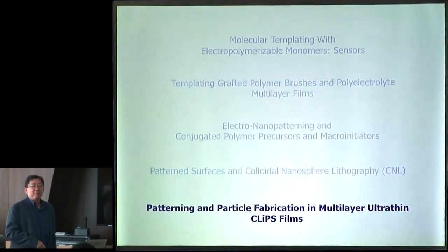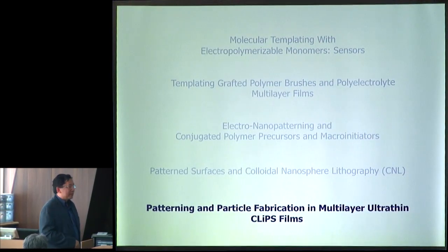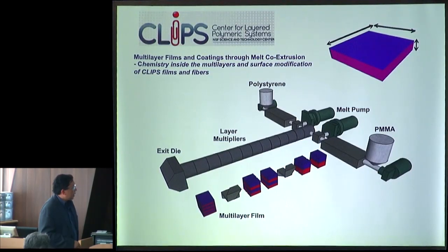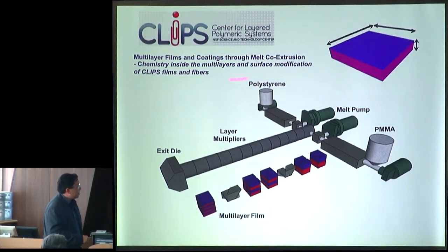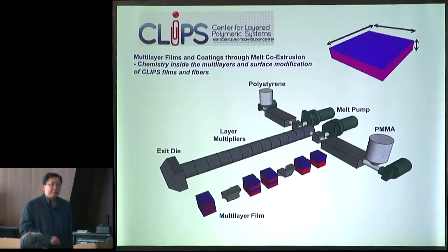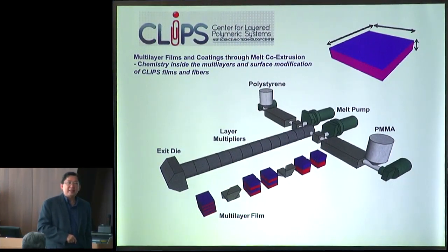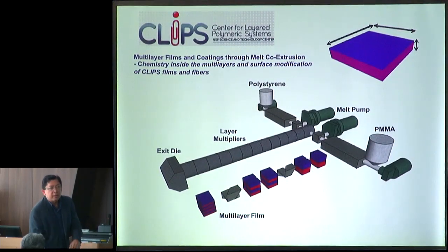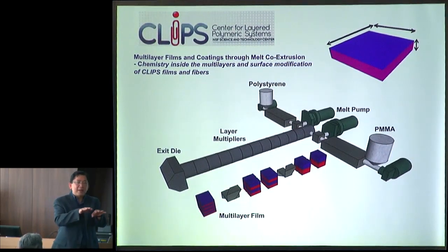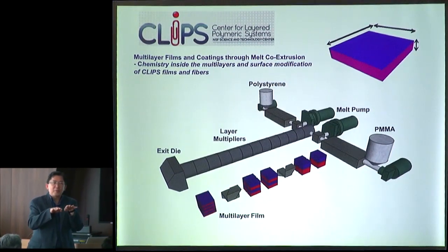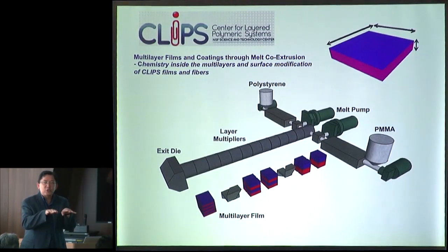So here is the polyelectrolyte. This is the polymer multi-layer that is different from the polyelectrolyte layer by layer that we've shown. Now, I'm a part of the center called CLIPS, and we can prepare multi-layer films by co-extrusion. What we do here, instead of the layer by layer of polyelectrolytes, we actually form the nanostructured layers by extrusion.